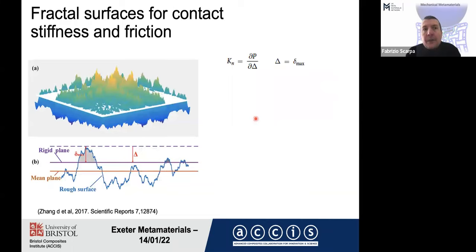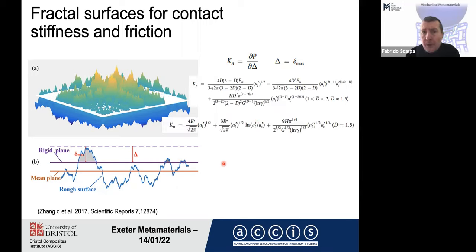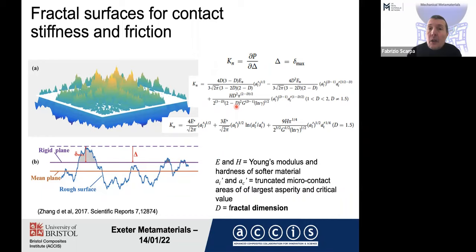I will finish this seminar mentioning something that, again, has been known for a while in open literature. If you look at works on Hertzian contact over a rough surface, quite a lot of authors, already 40 years ago, considered fractality for patterns of the rough surfaces. But what is interesting is that not only can you control the contact stiffness with the fractal order, but you can also control the friction and the energy dissipation. So in these papers, a few years ago, we introduced this model that was considering different geometrical aspects of the average rough surface through a mean plane, a rigid plane, and also this D factor that is the fractal order of the surface that we consider.